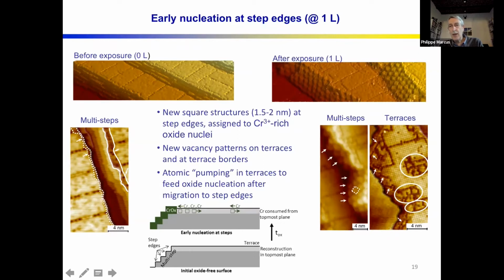So the initial oxidation takes place preferentially at the step edges. And we could assign this to chromium oxide nuclei because we know from XPS that at the beginning only chromium is oxidized. So that allows us to propose a model for the early oxidation in which this is the initial stainless steel surface. This is a terrace, and these are steps between two terraces. As you can see, we observe multi-atomic steps, and after exposure to oxygen, only the step edge here is covered by chromium oxide nuclei, and it's pure chromium oxide, meaning that chromium has been diffusing on the surface to the step edges. And of course, this means that there will be a depletion of chromium near the step edge.